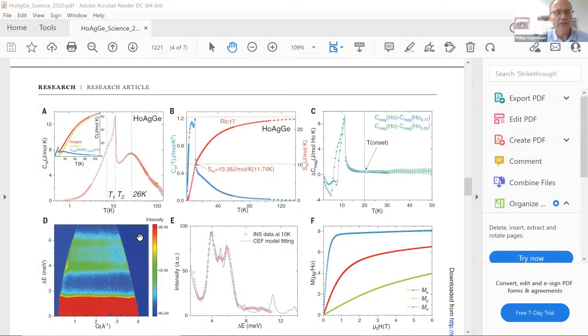So in case of the HoAgGe, we don't have an indication of missing entropy. So we studied, let me see whether I could quickly open our paper and show you the specific heat plot. If you just give me a couple of seconds. All right, so this is the specific heat, the different transitions in the specific heat. There is also a broad peak above the magnetic order, and then there are distinct signatures at the 2 transitions.